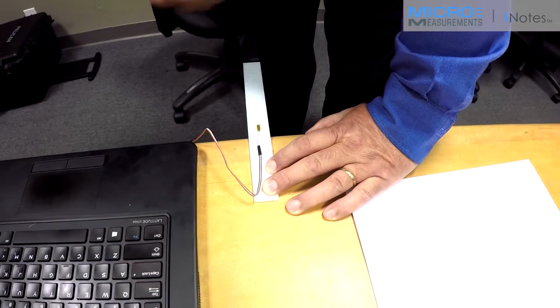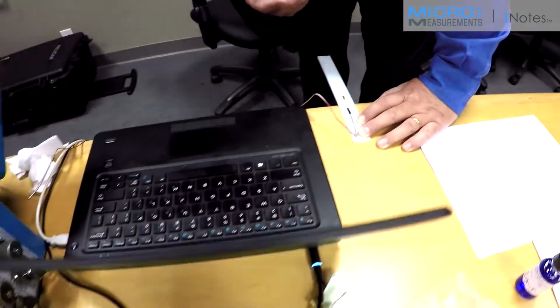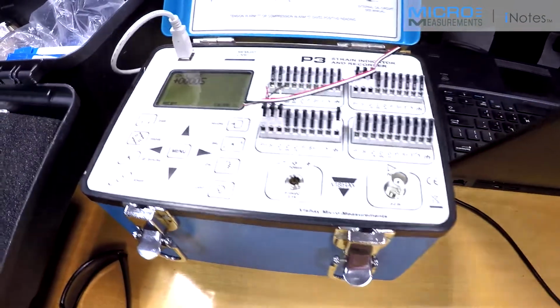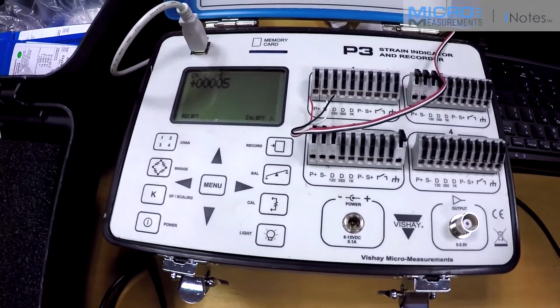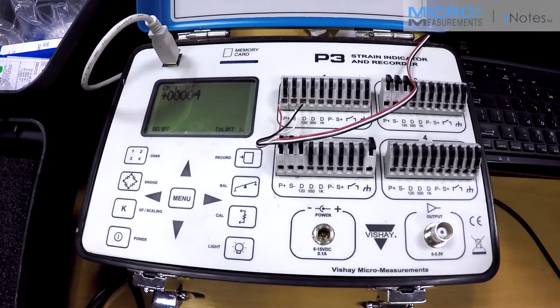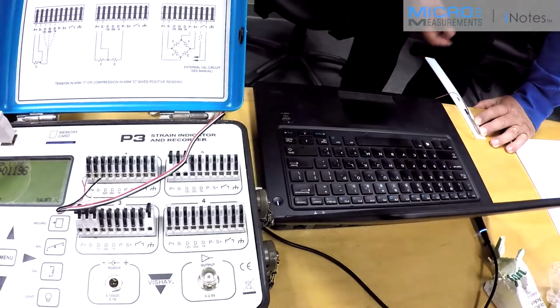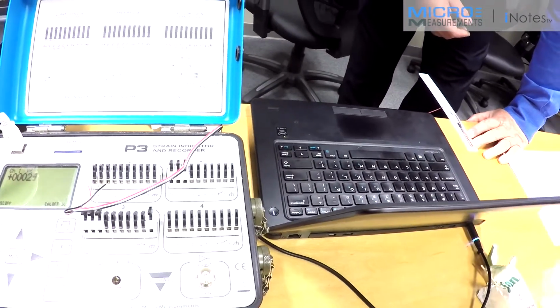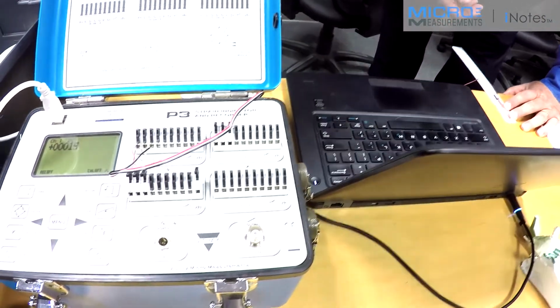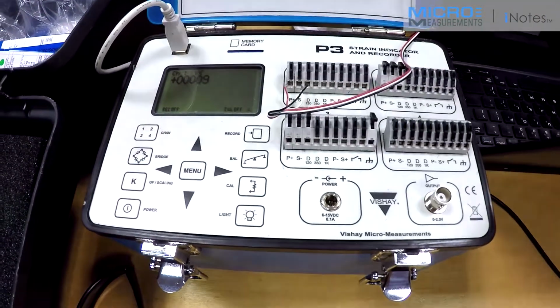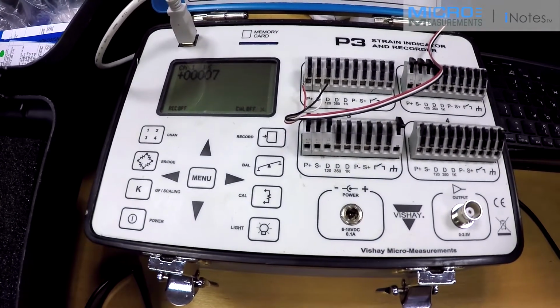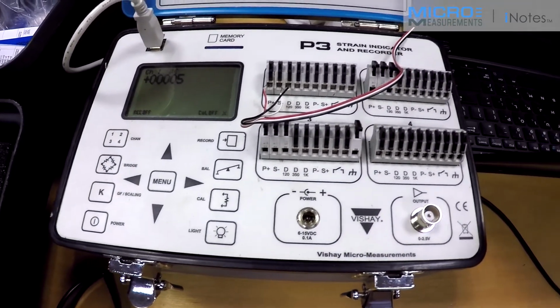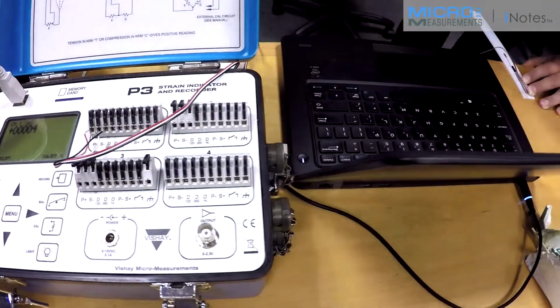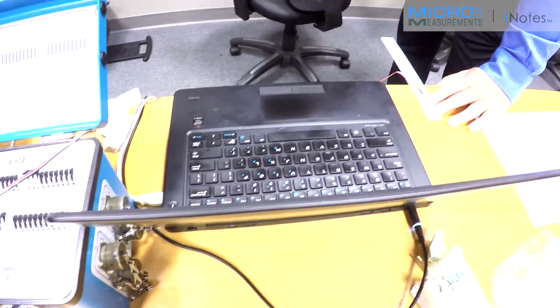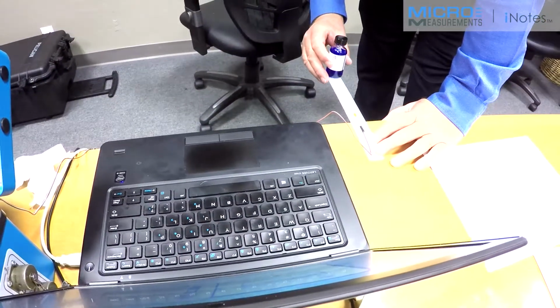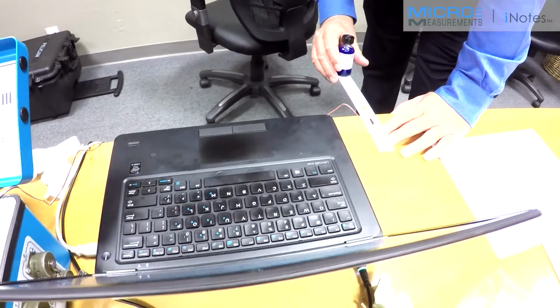If this was a good spring material like 2024 T4 aluminum, we would expect excellent zero return, within one count or even less. But we're seeing not only some failure to return, but you'll see over time the indication slowly creeps back to zero. If this had passed through zero and been a negative value, that would have been indicative of negative creep in the installation, but being this is showing a positive offset that's slowly counting down to zero, that indicates plus creep in the substrate material. So the gauge is following the material. It's telling us what's going on in the plastic.